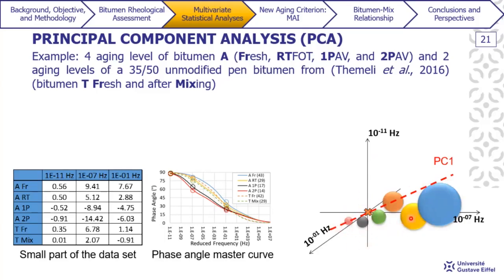And then we determine the direction of the best fitting line for PC1 that goes through the origin, that will be able to account for the most variation around the origin. PC2 is orthogonal to PC1 and accounts for the largest variation that hasn't been considered by PC1. And finally, PC3 is determined likewise. Here we have 3 PCs, and note that we have the same number of PCs as we have columns.